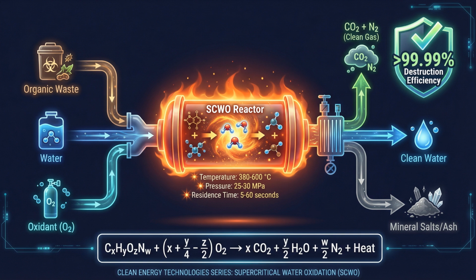Organic carbon converts completely to carbon dioxide. Nitrogen becomes nitrogen gas, not harmful nitrogen oxides, because temperatures are below thermal NOx formation. Chlorine, sulfur, and other heteroatoms convert to acids that can be neutralized. Destruction efficiencies exceed 99.99% for most compounds.